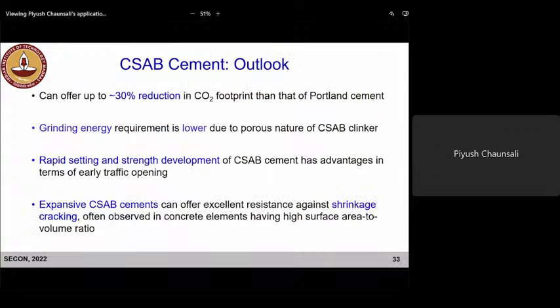So let me summarize what we discussed and where we are, and where current efforts are being undertaken. CSAB cement can offer up to 30% reduction in the CO2 footprint. So if you want to develop sustainable binders, this is a potential candidate. Grinding energy requirement is lower because of the porous nature of CSAB clinker, and you can attain rapid setting and strength development using CSAB cement, and it has advantages. Let's say you want to open the traffic early, because we don't want to hold things for a long time. In these situations, again, CSAB cement can be used.